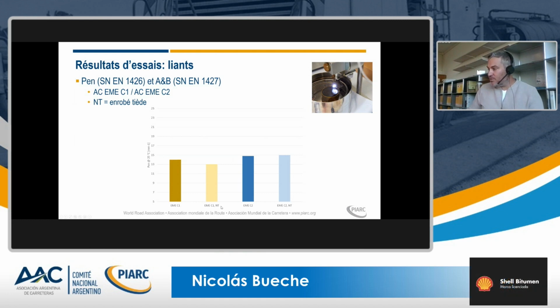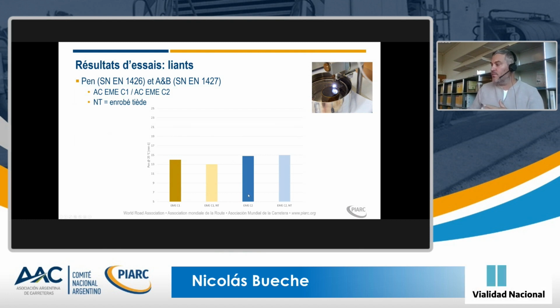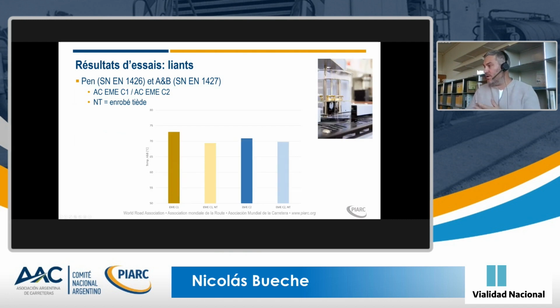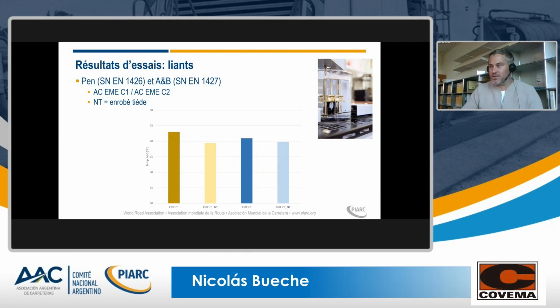On the graph, every index corresponds to warm mix. On the left-hand side you have the hot mix, then you have the warm mix for C1. The dark blue is the hot mix, and the light blue is the warm mix. If we consider the penetration or the ring and ball value, we didn't see that much difference. We have a bit lower value for the ring and ball value for the warm mix, which is quite logical if you consider the aging of the asphalt, but not that much difference.